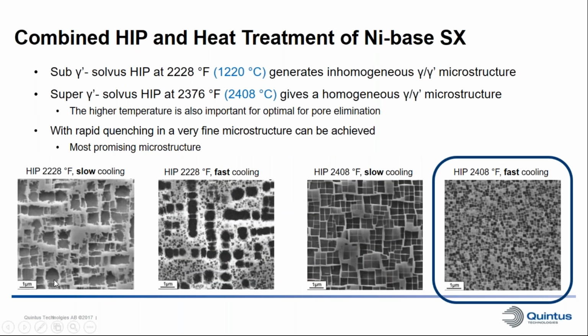If we look on the lower left here, we have the results from the below gamma prime solvus temperature. And we can see that we get quite inhomogeneous gamma prime microstructure, which is not what we desire. We cannot really see any difference between the slow cooling and the fast cooling in the HIP. When we look at the higher HIP temperatures above the gamma prime solvus temperature, we can see that we get a very nice homogeneous microstructure. However, we can see with the slow conventional cooling rate, we get quite a coarse microstructure. However, when we perform the rapid quenching in the HIP, we can get a much finer microstructure, which looks very promising for material properties.